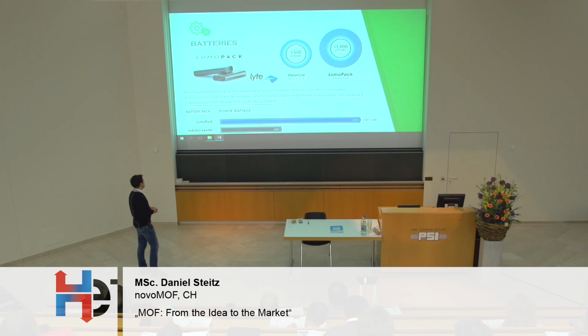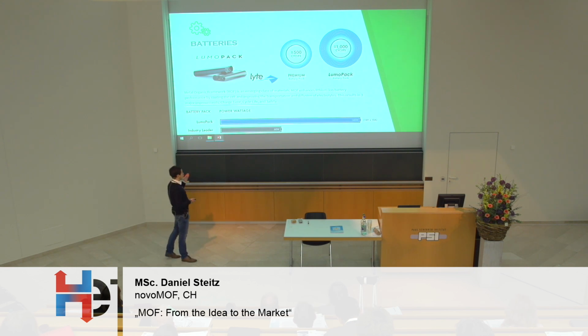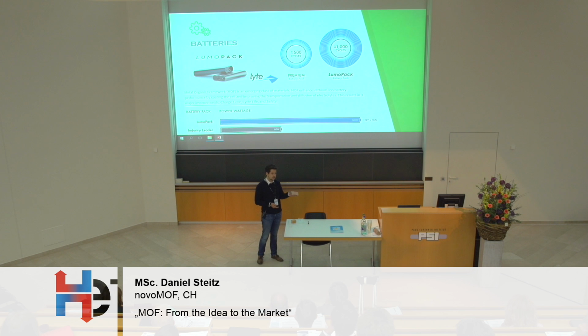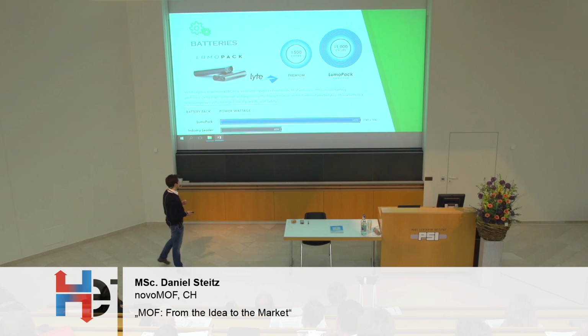They're also saying they're the fastest charging batteries. They say they can charge with 140 watts, which means this battery pack, which has 6,400 milliampere hours, can be charged within 18 minutes. Basically, if you took this technology and put it in an iPhone 6 or 7, you could charge the iPhone in 6 minutes. This is what is stated on the website. I couldn't confirm yet if it really charges that fast, but I can tell you later if you're interested. And we don't know exactly how they're using the MOFs inside, because of course they're a business and want to keep their business secrets.